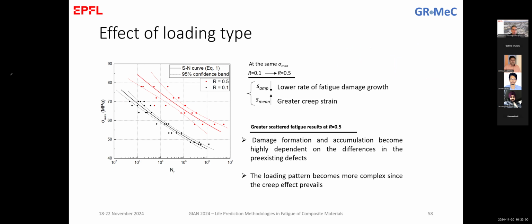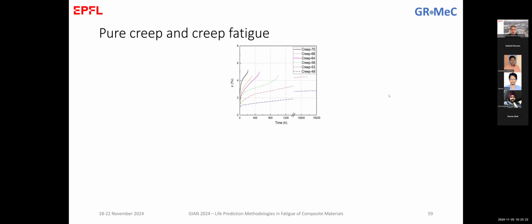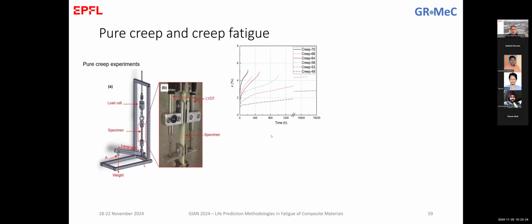So again, to the discussion that we had yesterday, here we see the fitting that we did, a simple power law fitting with the confidence bounds defined by ASTM E739, the typical fitting equations suggested by ASTM. So for the same testing, you remember we wanted to investigate the viscoelastic effect, so we did pure creep testing. And these are the results, typical results of creep for different stress levels.